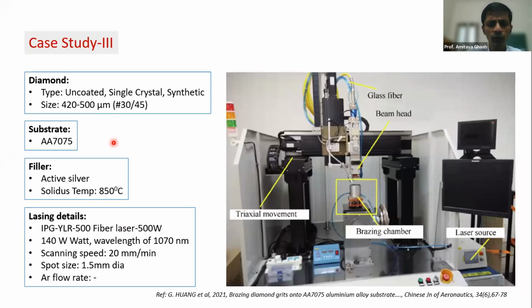So in many grinding tools, we observed that if they're made of modern-day aluminum alloys, they're pretty advanced, and they can really sustain the grinding loads and all those things involved. And the 7075 is even used for making resin bonded wheels. So I think the group decided, why not attempt this particular alloy for brazing of the diamond. In this case, they used a fiber laser of 500 watt, but of course the utilized power is restricted to 140 watt. The scanning speed is 20 millimeter per minute, spot diameter is 1.5, again in an argon environment.